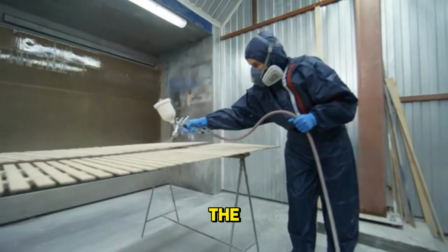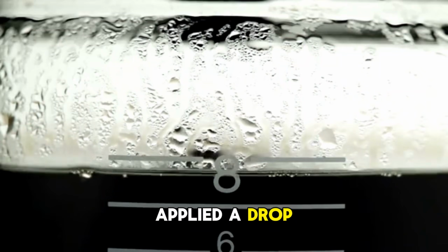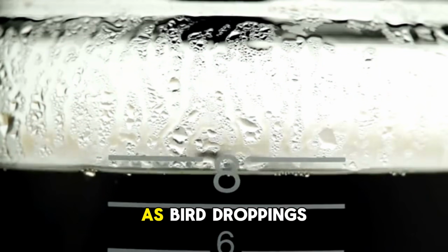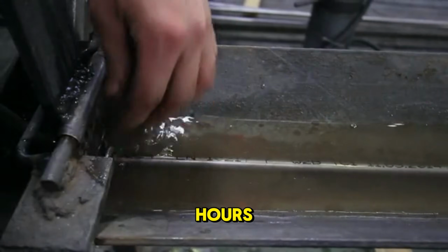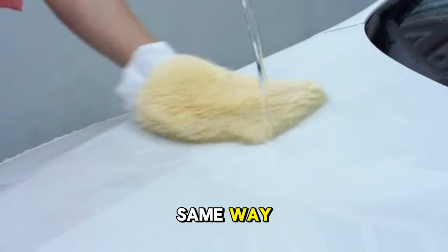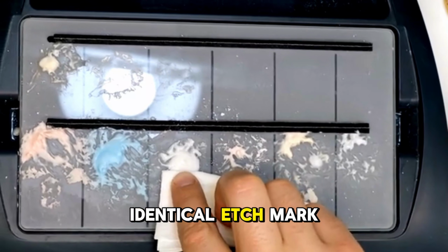Ran the same test on the CO2 panel deliberately. Applied a drop of acidic solution at the same concentration as bird droppings. Left it 6 hours. Removed it the same way. Inspection result. Identical etch mark.